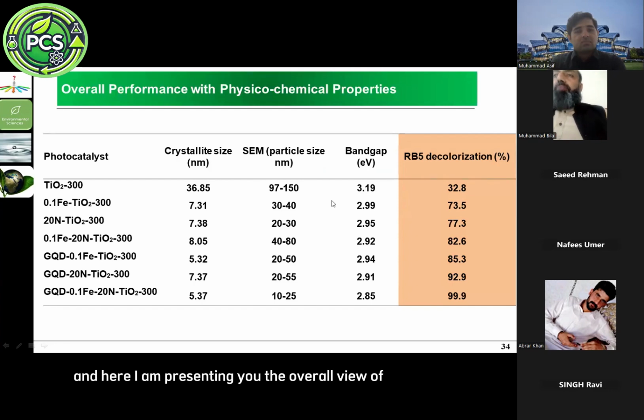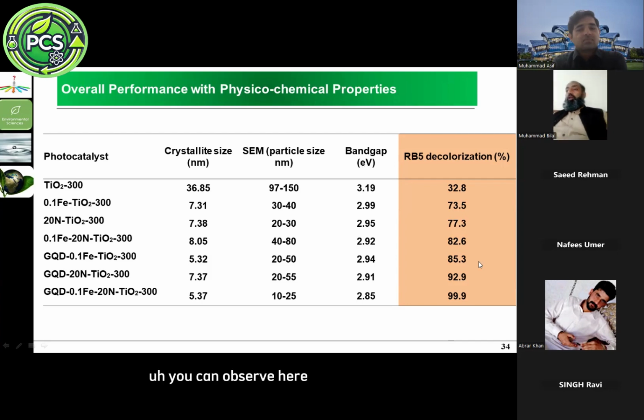And here I am presenting you the overall view of the whole study, what we did in the lab. We observed at 30 milligram of the level of the contaminant in the solution. You can observe here titanium dioxide with this crystallite size, SEM particle, and band gap. We observed 32% RB5 decolorization, followed by the iron titania, 7.31, 30 to 40, bandgap 2.99, 73.5%.